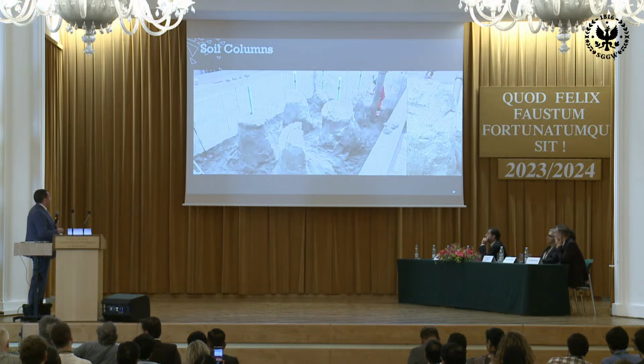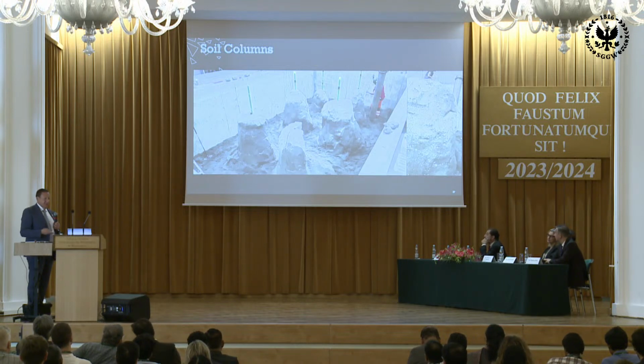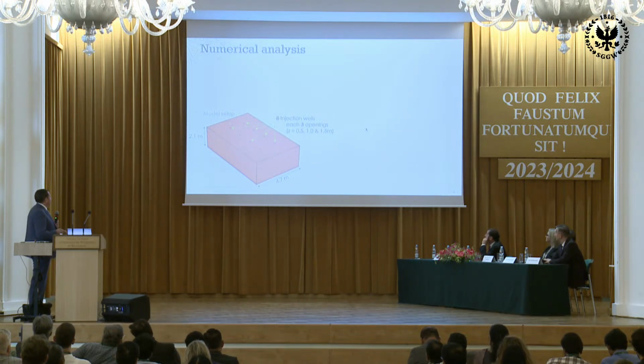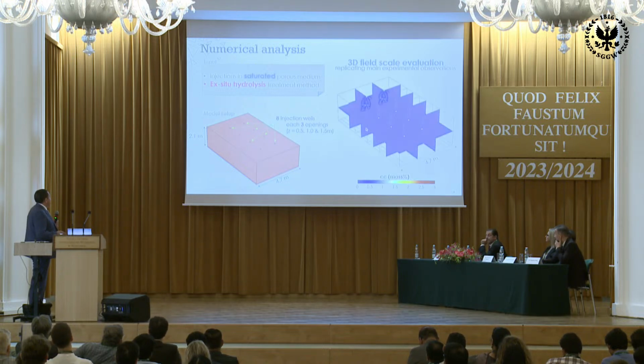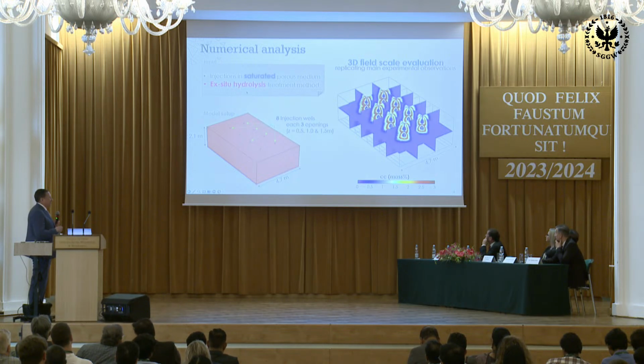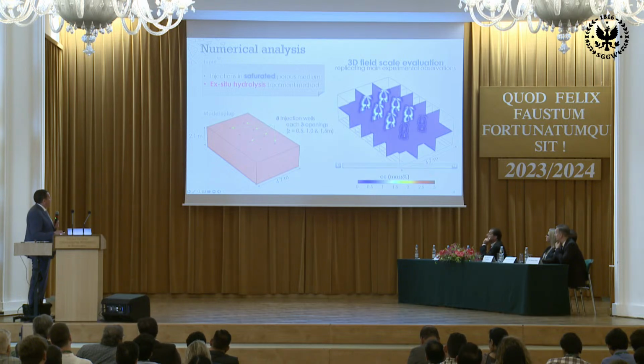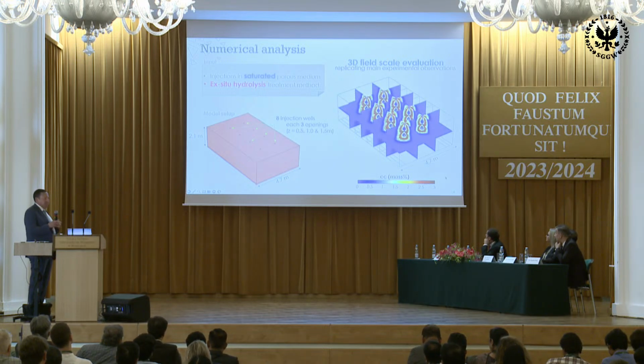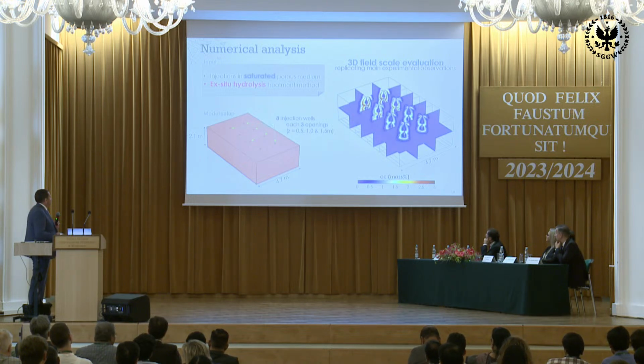Now the question is, how are we able to simulate and to predict the mechanical behavior of the material after cementation? Before going there, I show you ways of validating the model. Here I'm showing you a case of injection in saturated soil in an ex situ hydrolysis process, and without going into details, what we can show is that our numerical finite element analysis allows us to get the calcite precipitation and diffusion, and allows us to control the pressures to inject and different conditions.